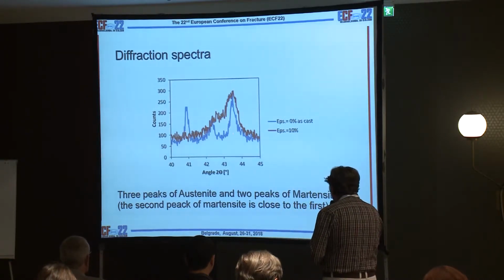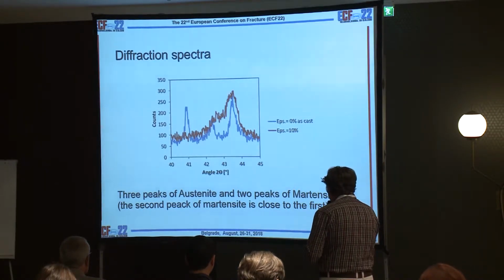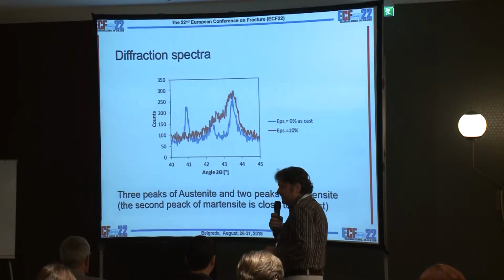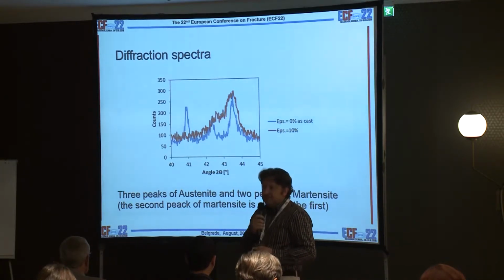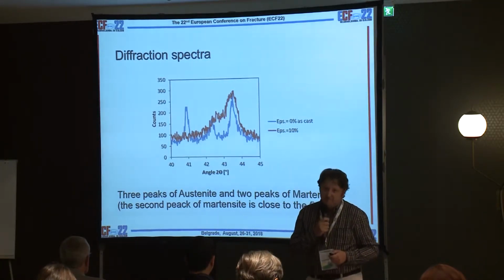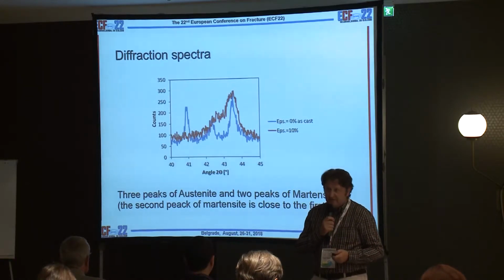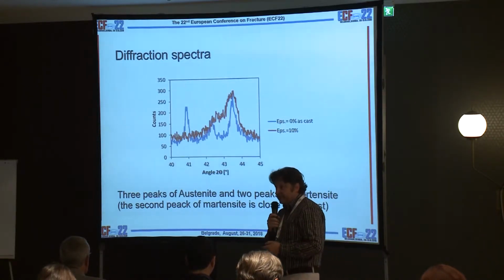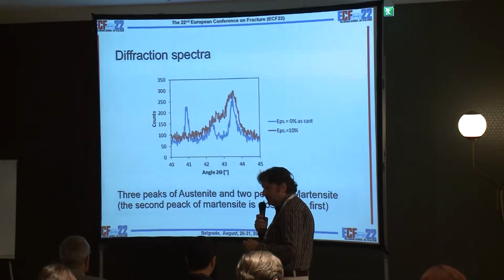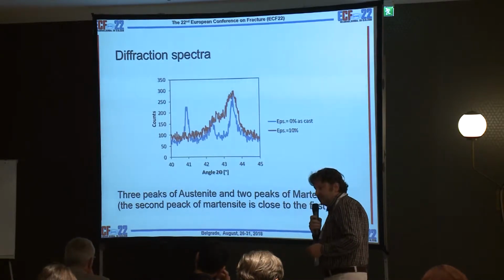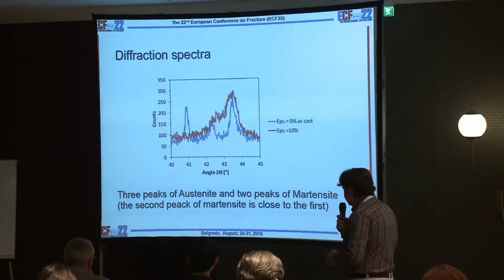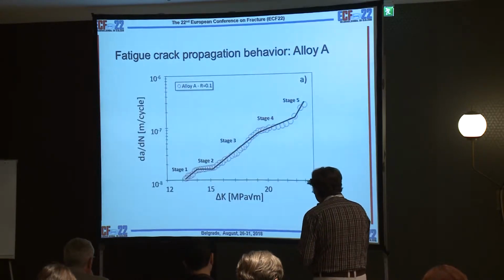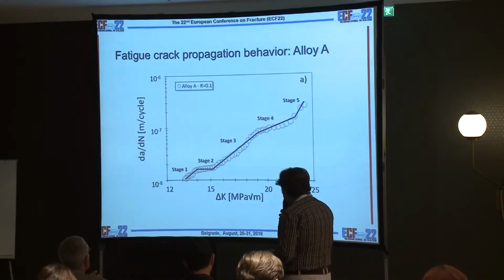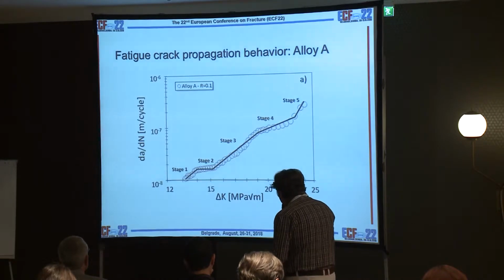Here you can see this peak present in loading and unloading conditions. This peak is stable. We think this is the peak corresponding to the habit plane, which is the plane where the transformation, direct and reverse, takes place. So, this is the first result in terms of